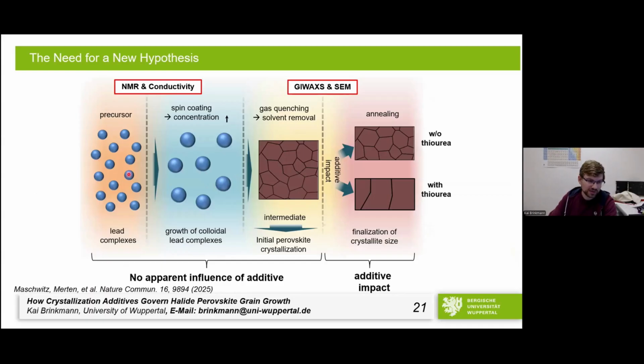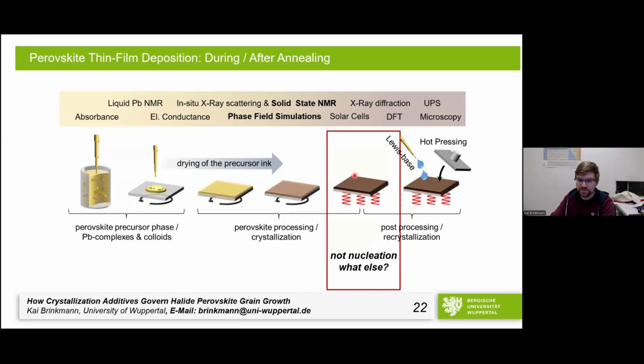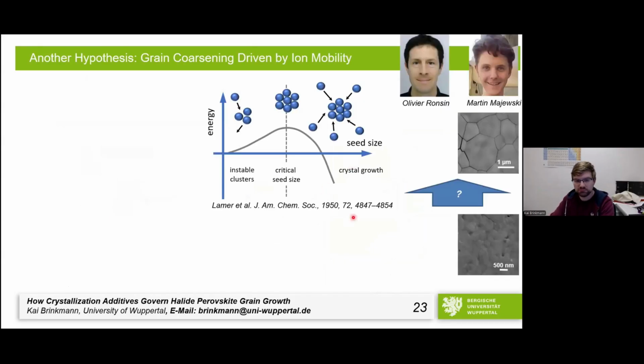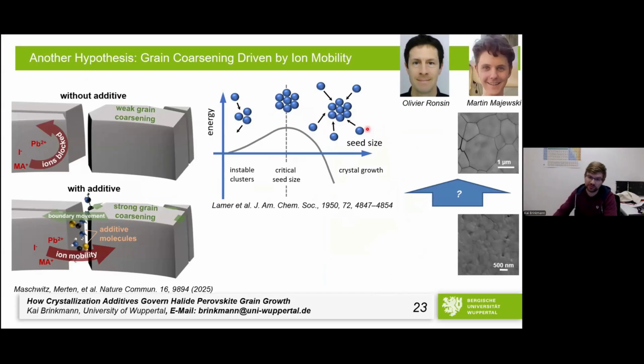So this is like a little bit of a sketch of a working hypothesis. So you basically have your precursor, you have your concentration, during spin coating, the colloids grow, you will get these grains, these nuclei, they will grow, it will form your perovskite. But this already well-formed perovskite, the distinguishing between without the additive and with the additive, then happens the moment when you put it on the hot plate. And we asked, of course, ourselves, why? Because, well, I think we all can agree that if there's no solvent in them anymore, if the perovskite is already there, we cannot talk about nucleation anymore. So we had to come up with another hypothesis, another explanation for how this comes to pass.